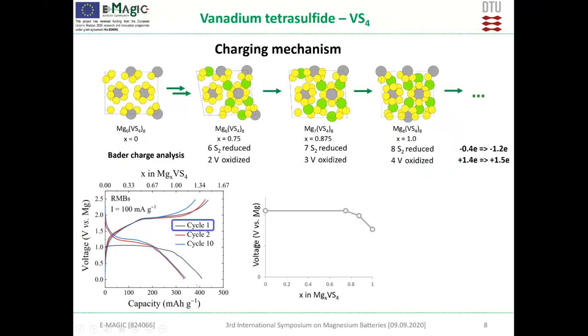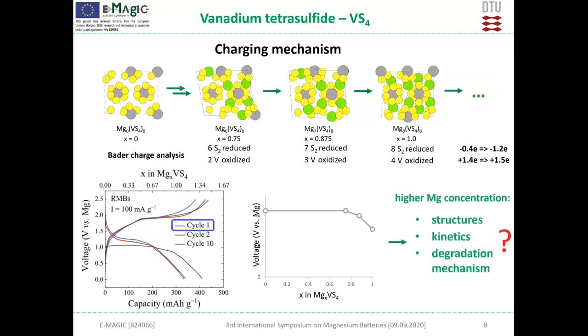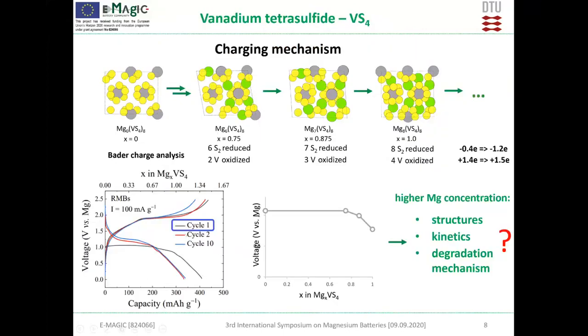This is still ongoing because it's a very difficult region of the cathode, and we are trying to find what is the structure there, how it impacts the kinetics, and what is the degradation mechanism, because we can see that after going here, the cathode behaves in a completely different way. So far, what we see in the calculations is that the bond between vanadium and sulfur is very weak when there is a lot of magnesium close by. So probably we will observe the formation of MgS inside the cathode, and probably this is the degradation mechanism that is causing the complete change of the shape of the curve.